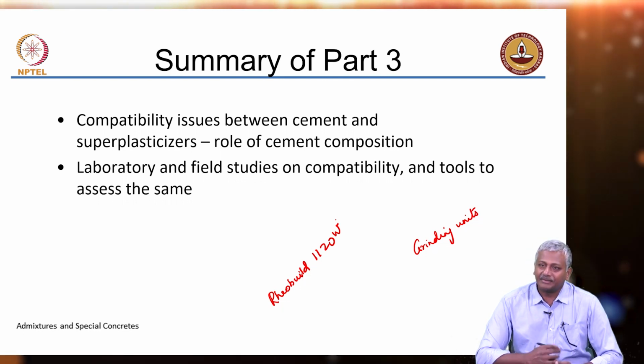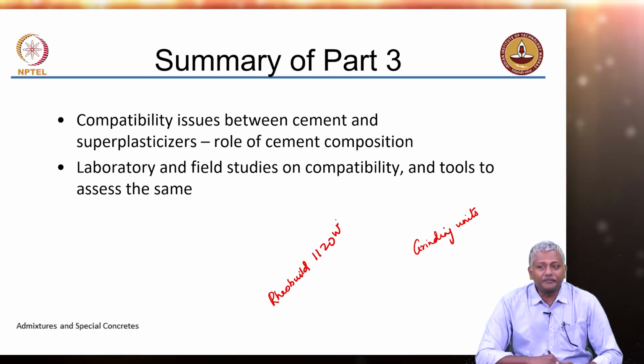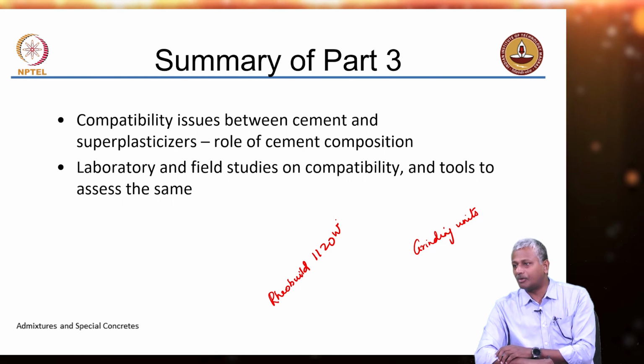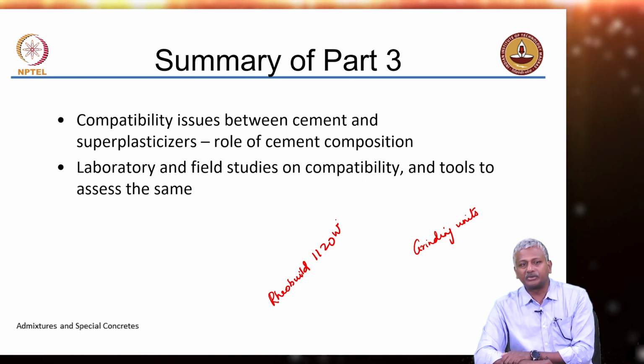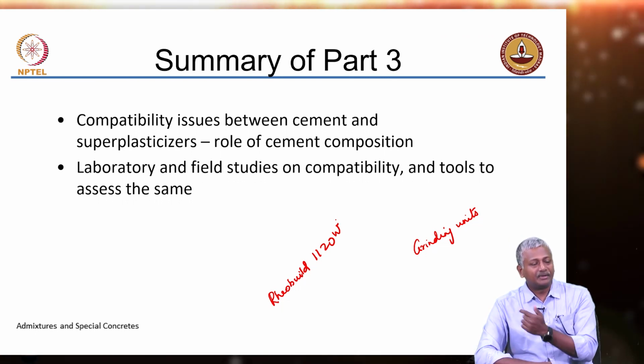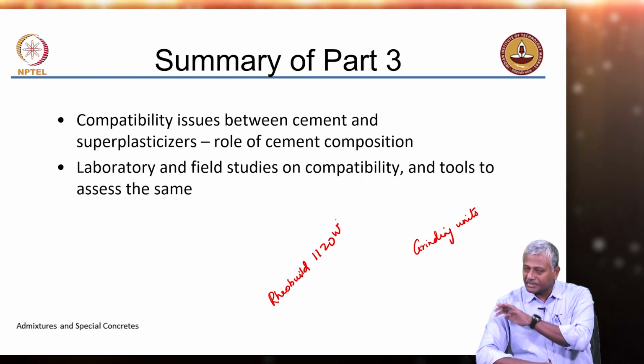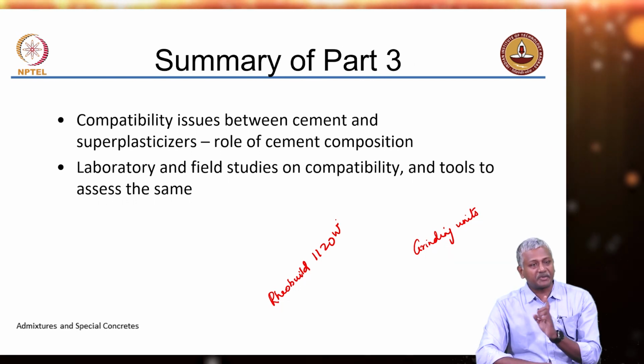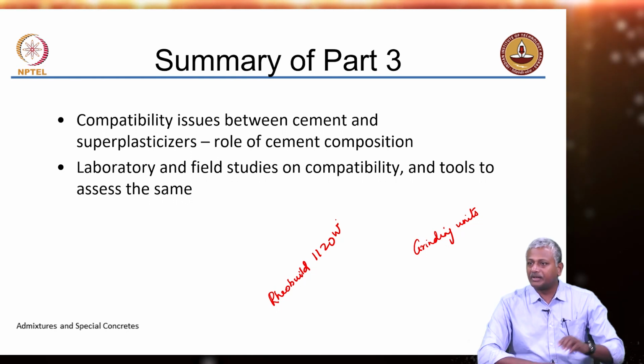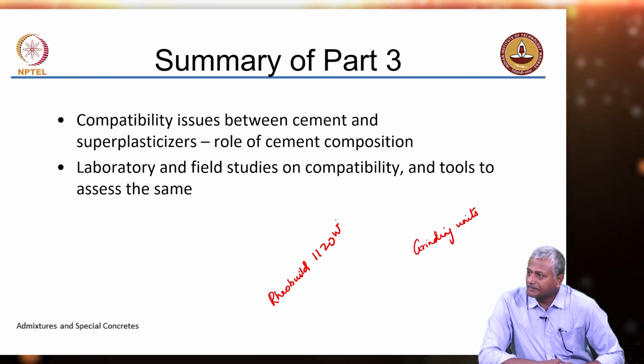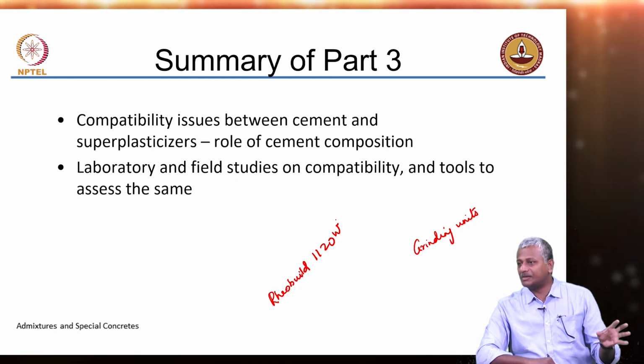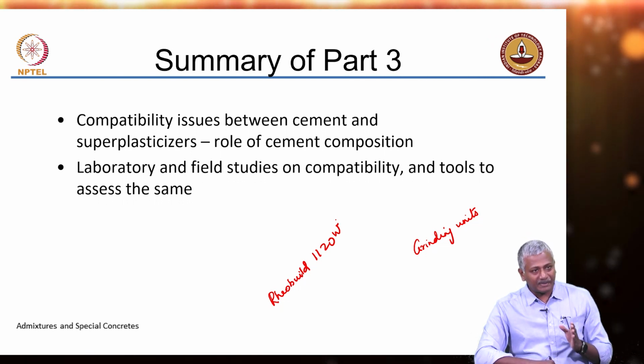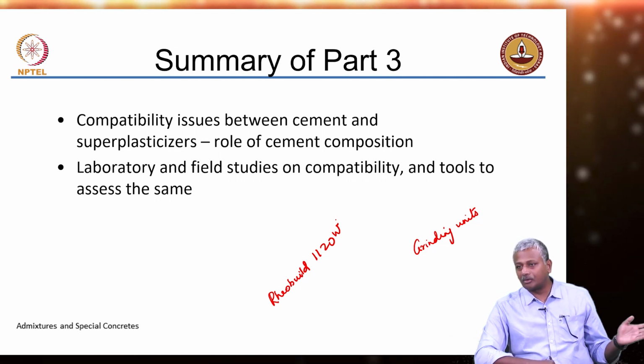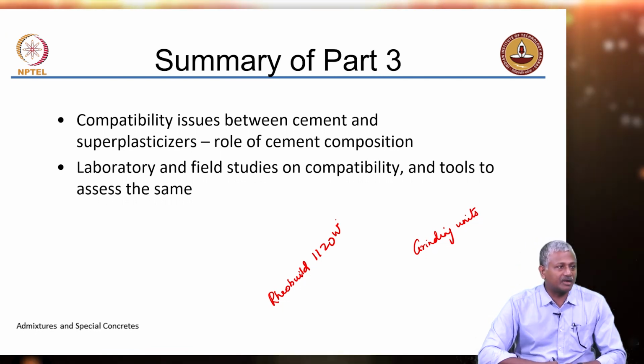If they had had the same concrete supplied with a pan mixer, which they ultimately did, they found a batching plant that was about 30 minutes away from this job site. They went to that batching plant and had the batching plant supply the concrete which was mixed in a pan mixer. Their workability was maintained consistently. So, here they were on the site with a tilting drum mixer which was absolutely not up to the mark to mix a concrete which had such a low water content of 130.